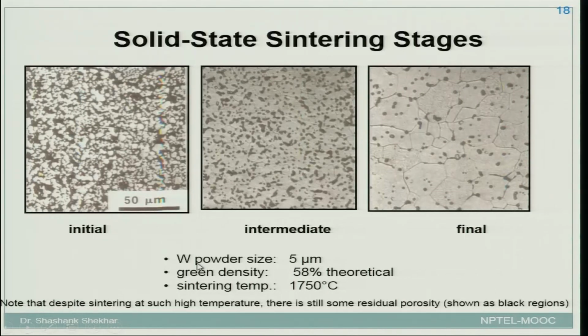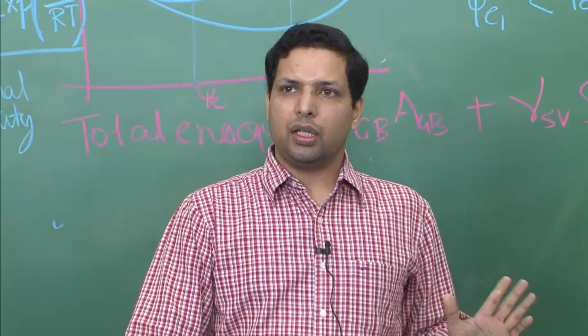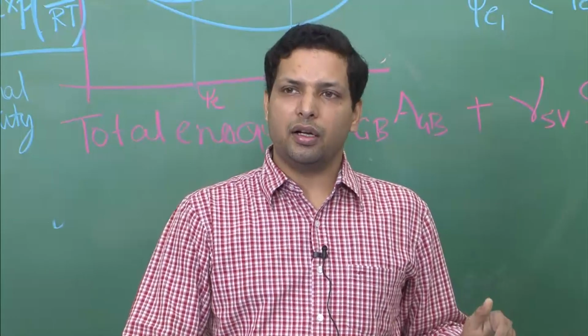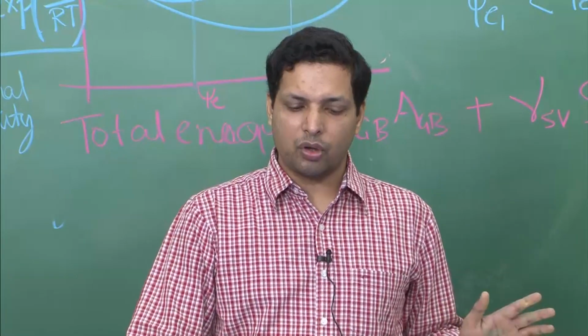Here again you have tungsten powder, which has a very high melting point. You see that the green density is 58%, which is very low, and at the end of the final stage of sintering at 1750 Celsius you still get some pores. There are still a large number of pores because the sintering temperature is relatively low for tungsten, which has a very high melting point. These are the different stages of sintering. So this covers the sintering concept in powder processing.